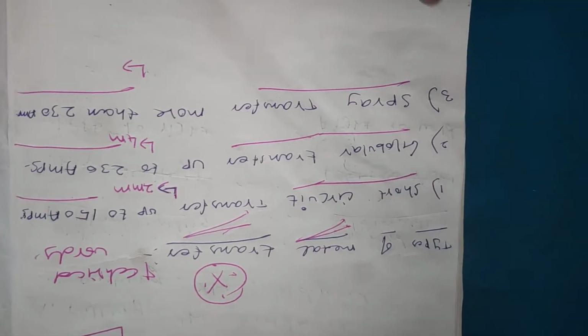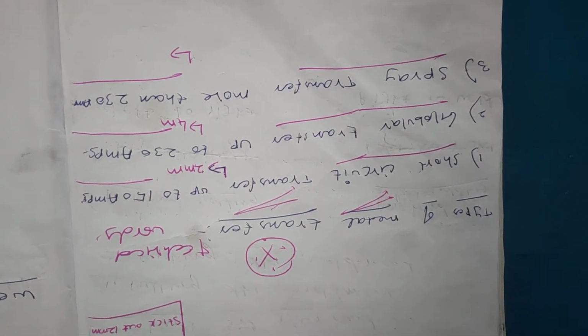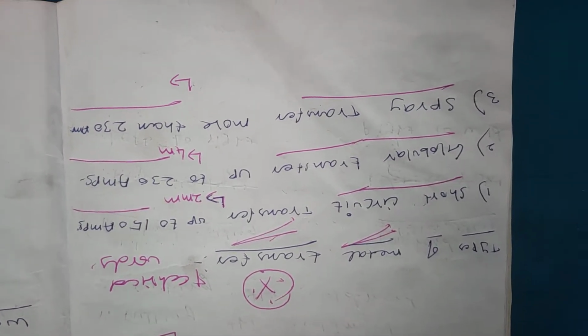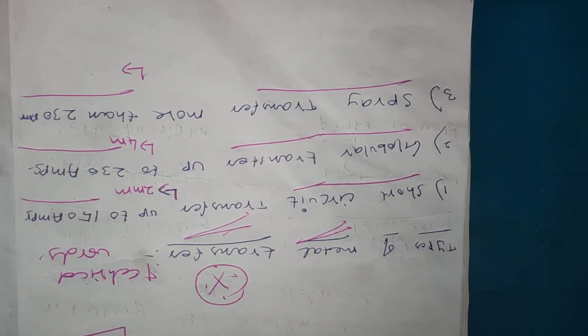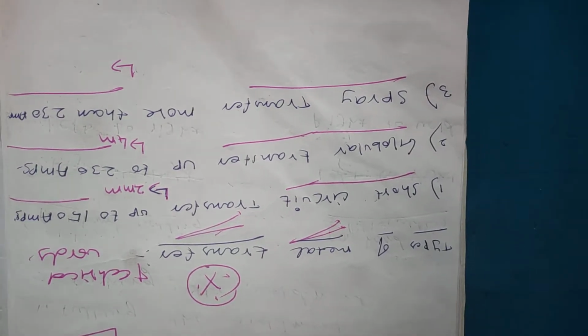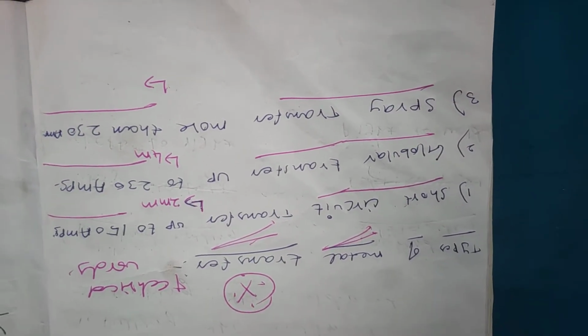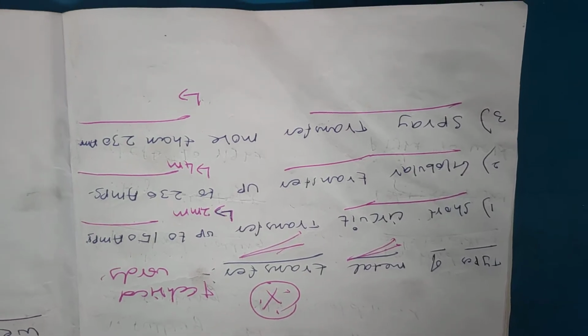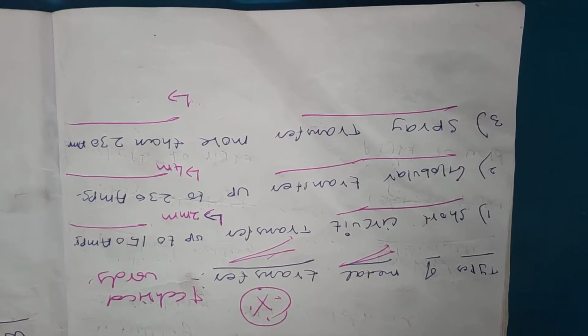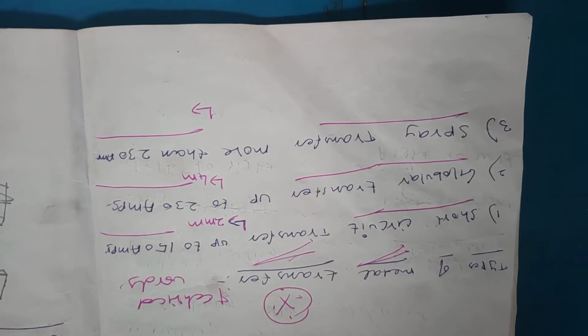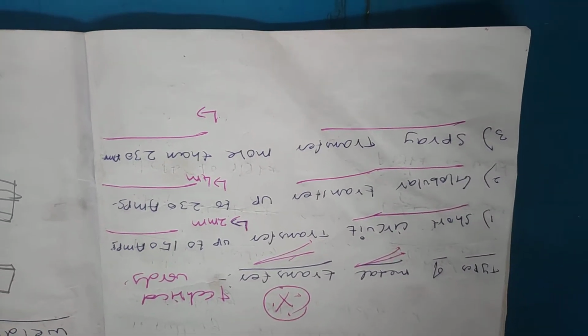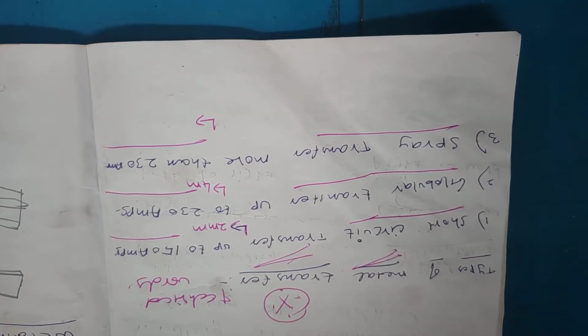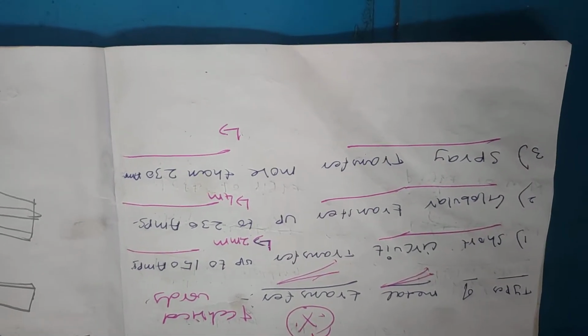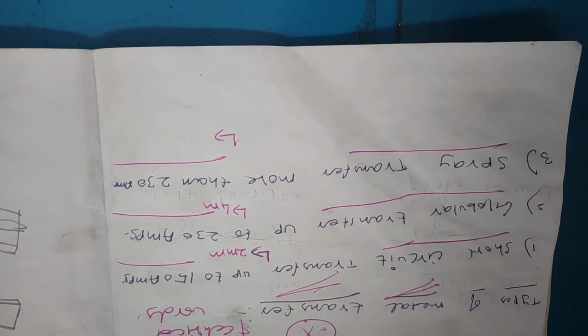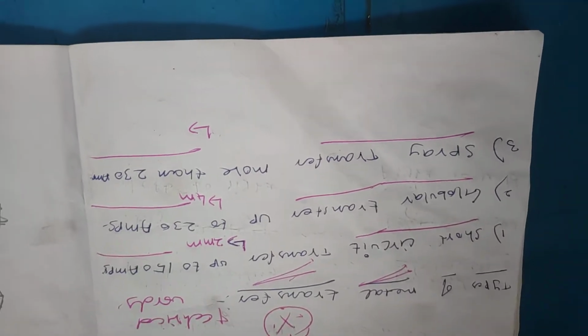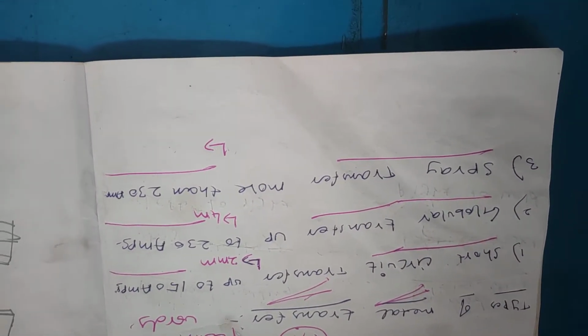This is for short circuit transfer. The amps required is 150. For 2 mm we use short circuit, and globular transfer is from 150 amps up to 230 amps, and for spray transfer we have to use above 230 amps. For 2 mm thickness of material we use short circuit, for 4 mm we use globular transfer, and for more than 4 mm thickness we can use spray transfer.